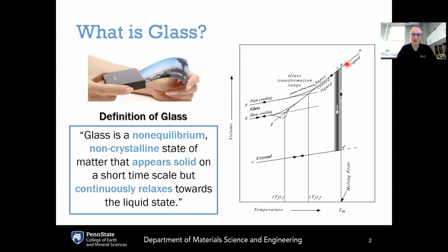And if you were to cool the liquid fast enough so that you don't give the atoms enough time to rearrange themselves into that ordered crystalline configuration, then that liquid can be quenched into the supercooled liquid state. And that supercooled liquid state, upon continued cooling, can be quenched into the glassy state. And the glassy state has a frozen-in liquid-like structure that comes from this quenching process. And so if you cool any liquid fast enough to avoid crystallization, it can, in principle, be quenched into the glassy state.